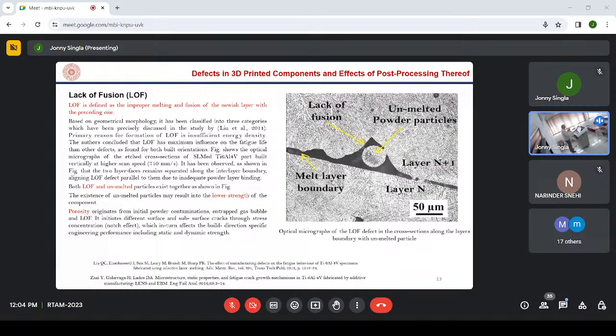The figure shows the optical micrograph of the etched cross section, taken for titanium 6Al4V, part built vertically at a higher scan speed, 710 millimeter per second. It has been observed, as shown here, that the two layer faces remain separated along the interlayer boundary, aligning the LOF defect parallel to them due to inadequate powder layer binding. Both LOF and unmelted particle exist together as shown in the figure. Now this round particle is the unmelted particle. Both can exist together,